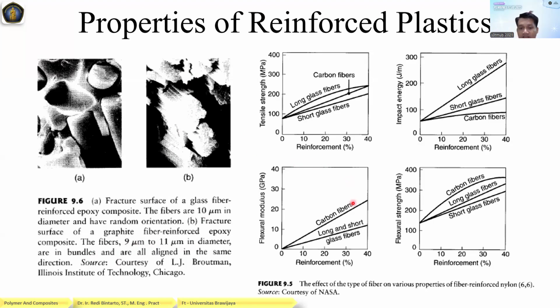So what is the effect? The effect on the material. This is an example, there's a carbon fiber. The tensile strength, impact energy, flexural modulus, and flexural strength are different when there is a carbon fiber, long and short glass fiber. Yeah, the carbon fiber has more flexural modulus, but we can see here impact energy. Carbon fiber is the lowest. So we can compare the carbon, and when we want to choose short and long fiber, glass fiber, yeah. And for the flexural strength and flexural modulus, carbon fiber is the highest.